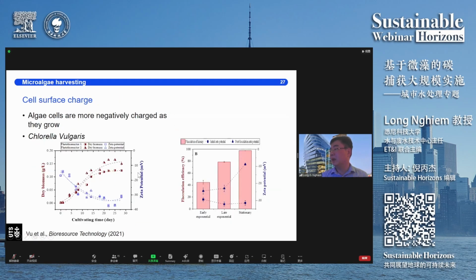So we carry out a set of experiments where we take the sample from a 350 liter microalgae reactor, and we take it at 3 different stages. The early exponential, the late exponential, and the stationary stage, and we do the harvesting. With regard to the surface charge of the microalgae cell, you can see here in the blue set of data that the microalgae surface charge becomes more negative as the solution matures.